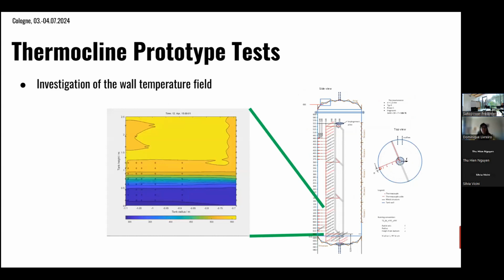This was a more recent investigation, where we focused on the temperature field in the near wall region, because the question was how stable the thermocline will be during standby periods. And also what we were interested in was the difference between the thermocline profile inside the molten salt and the temperature profile in the tank walls. Because when you investigate tank wall stresses and so on, you want to know what kind of temperature you have to expect. And all we typically know is the temperature field inside the molten salt and how that was linked to each other.